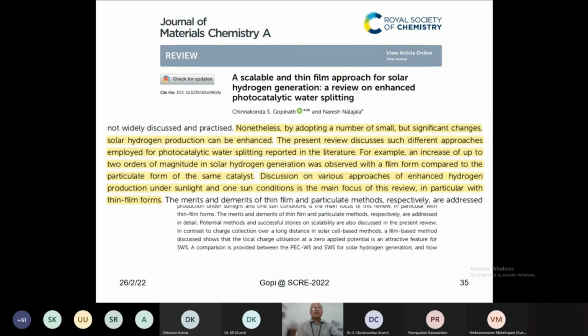Let me go through this couple of lines that we have written. By adopting a number of small but significant changes, solar hydrogen production can be enhanced. The present review discusses such different approaches employed for photocatalytic water splitting reported in the literature. For example, an increase of up to 2 orders of magnitude in solar hydrogen generation was observed with a film form compared to the particulate form of the same catalyst. Discussion on various approaches of enhanced hydrogen production under sunlight and one-sun condition is the main focus of this review, in particular with thin film forms.